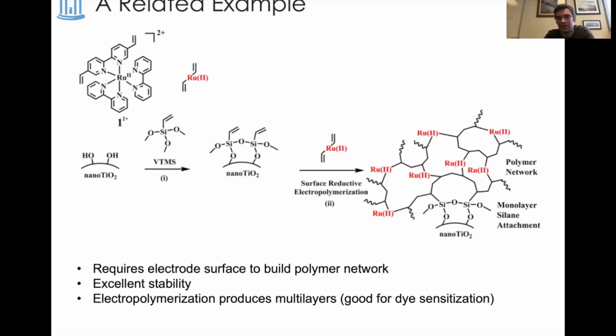So there's pros and cons to this. The advantage, especially considering this is a light absorbing dye, and that the goal of this work was to sensitize the transparent TiO2 to visible light, is that you get a large number of ruthenium complexes near the surface. This is not a perfect monolayer by any means, and you get sort of a polymer network of complexes that is going to increase the light absorption profile. The cons are that it's not a very well-defined surface. So being able to, for example, get substrates to some of these ruthenium complexes may be harder than one would like. So there's trade-offs in this approach versus the azide click chemistry on the prior slide.